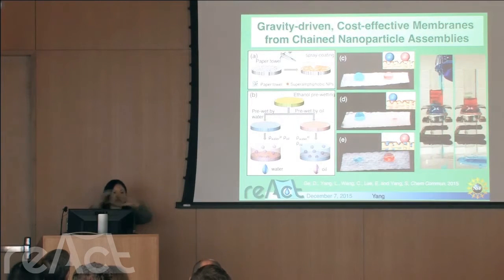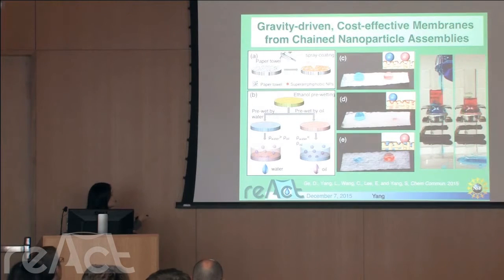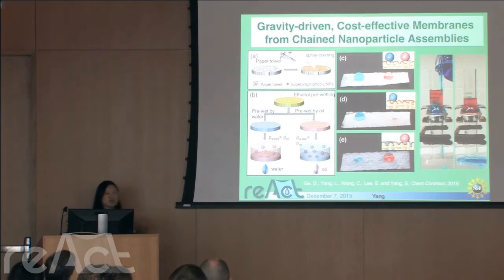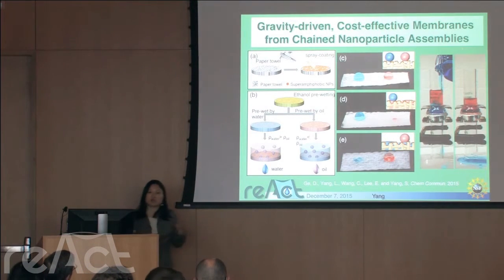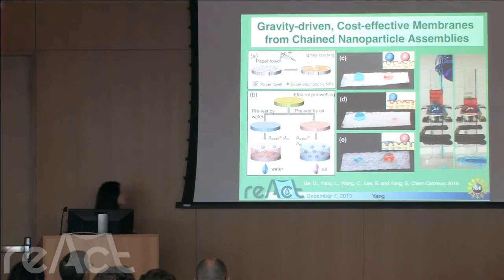Which means you can transfer this by simply spray coating onto a paper towel, the paper towel we use all the time in our lab. This is a microscopically porous support, and then we spray those nanoparticles on top of it. Because it's amphiphilic, we can make it water wettable or oil wettable, so we can use the same substrate to separate the oil or separate the water by engineering the wetting condition.